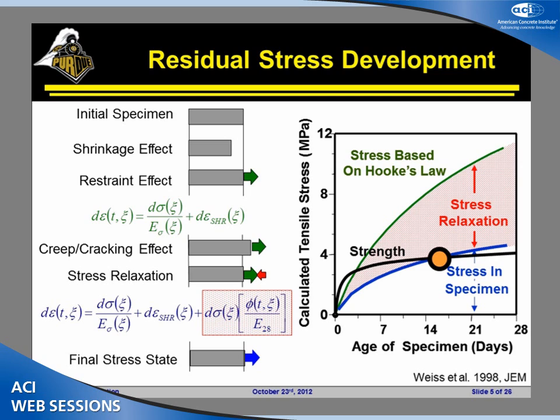So by the time we start to formulate this equation, we've started to see we've got shrinkage involved, we've got modulus involved, and we've also got the creep involved in the system. Now, if we think about the case that I was talking about before, where we go to a lower water to cement ratio system with maybe a slightly higher paste content, we know that the modulus is going to go up. We know that the creep is going to go down. Both of those factors, right? If we have less creep, the stress goes up. If we have a higher modulus, the stress goes up because we have to pull the system with more force to bring it back to that zero displacement.